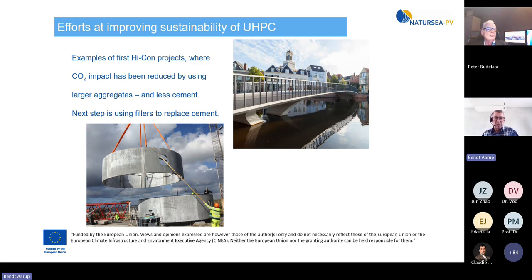And one way of improving is to reduce the cement content, as you also found out or know in the Natursea project. We've done some projects where we introduced larger aggregates in a UHPC. Normally, what we used in the factory until about 2 years ago was a mortar with a maximum aggregate size of 4 to 5 millimeters. But by putting in larger aggregates up to 8 millimeters, we could reduce the mortar content and the cement content. And this was done for the top being some segments for a windmill turbine tower, and the bottom for Catharina Bridge in Holland, a small bridge. So this is one way where we can reduce cement content.